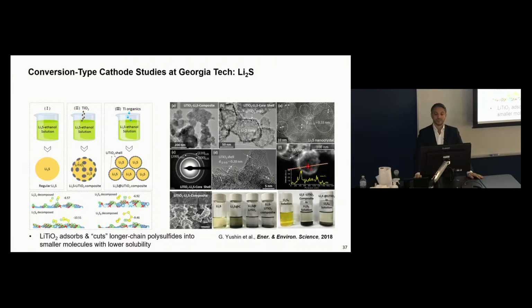You also don't have to use, certainly, carbon. You can use a variety of other materials as a shell. And what we found is that many oxides have very interesting properties. Some of the shells that we tried to produce were not formally conformal. They have holes, and yet they help to retain stability of these materials, which was very puzzling for us. Later we realized, in collaboration with Oleg Borodin from Army Research Lab, who had done some modeling, that these long-chain polysulfides decompose on the surface of many oxides and form much shorter chain polysulfides that have dramatically lower solubility in the same electrolytes. So you simply dramatically reduce solubility of the byproducts that you potentially form.